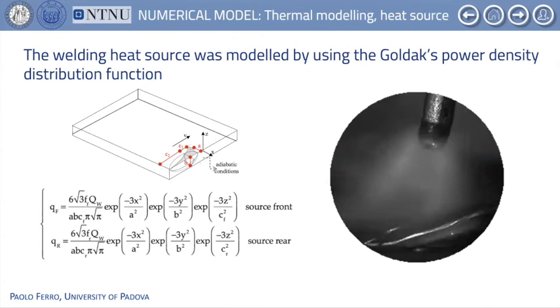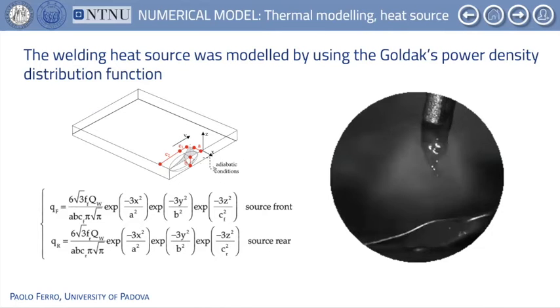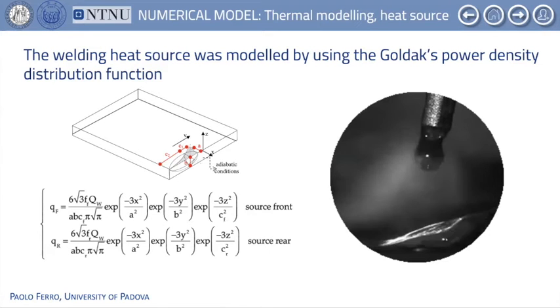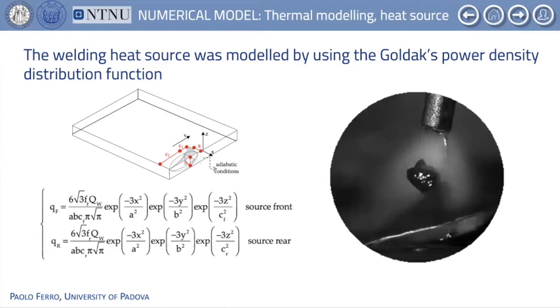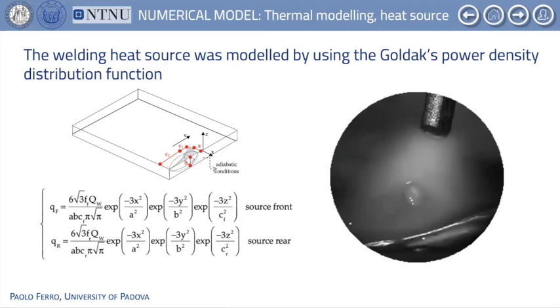The heat generation due to the heat source moving over the weld line is described by the power distribution function proposed by Goldak in 1984 for arc welding processes. Gaussian parameters of the Goldak heat source were chosen in a way that they produce a proper molten weld pool. Radiative and convective heat loss was modeled using the Stefan-Boltzmann law and convective heat transfer coefficients respectively.